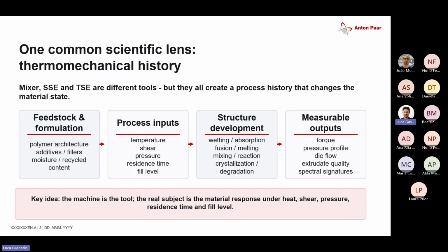And with these input parameters, what we want to do is finally an optimization of the whole process. What gets into this process, for example, in the processing chain for polymers, could be to achieve a certain degree of crystallization of your polymer, optimize the reaction time with the addition of additives, optimize the fusion behavior through the addition of certain kinds of lubricants, and in general stabilize the melt stability.